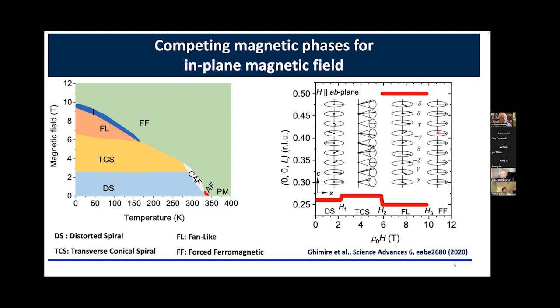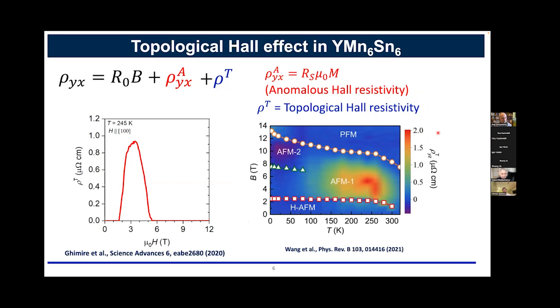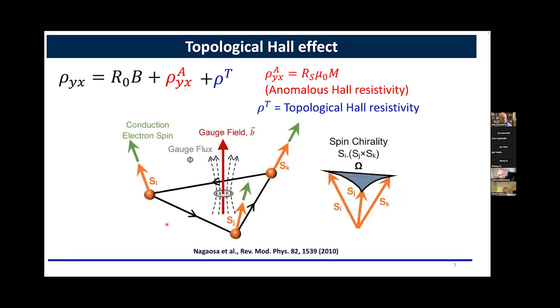And one of the highlights in this material was the observation of the topological Hall effect that comes especially at higher temperatures, and you don't see it at lower temperatures. At one particular temperature, if you look at 245 Kelvin, for example, you have this nicely peaked topological Hall effect within a certain magnetic field. Now the question is, where does this topological Hall effect come from, right?